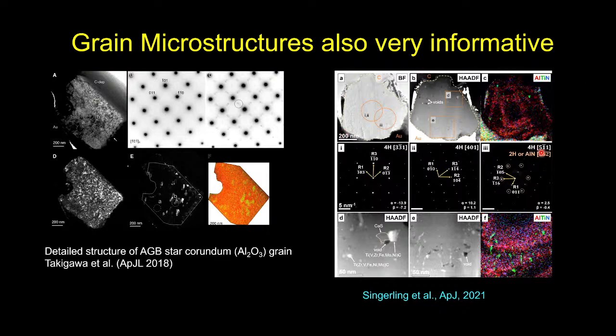These are some similar measurements, but of silicon carbide grains, and what we're looking at are element maps. This is a silicon carbide grain. That's just kind of what it looks like in electrons. But when we look at the chemical map and the scale here, that's 200 nanometers. So the detail we can do this is insane. You can see there's little subgrains of titanium carbide, these green things. But you can also see that there's aluminum, and it's not homogeneous, that this thing has growth rings, where when this grain was crystallizing in a wind of this AGB star, the amount of aluminum was either changing, or the temperature and pressure conditions were changing as this grain condensed to have different amounts of aluminum go into the structure. And then to interpret this, you have to go into detailed thermodynamic modeling and material science knowledge and all this. But it's very, very informative. Again, unique information about stars by studying microscopic bits of dirt in the laboratory.